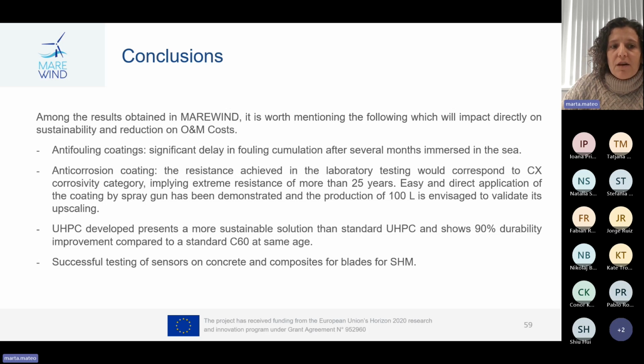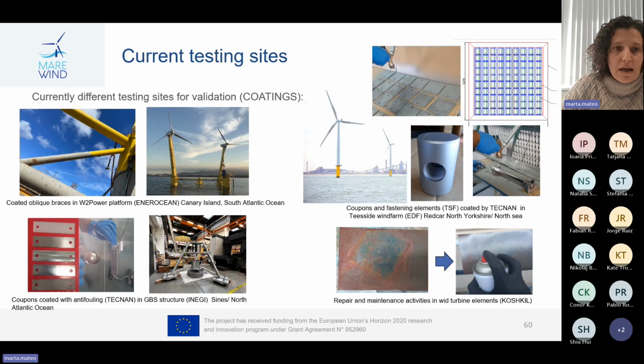Easy and direct application of the coating by a spray gun has been demonstrated, and the production of 100 liters is envisaged to validate the upscaling. And according to the concrete, the ultra-high performance concrete developed presents a more sustainable solution than the standard ultra-high performance concrete, and shows 90% durability improvement compared to the standard C60 at the same age. Finally, also successful testing of sensors on concrete and composites for blades has been achieved in the project.